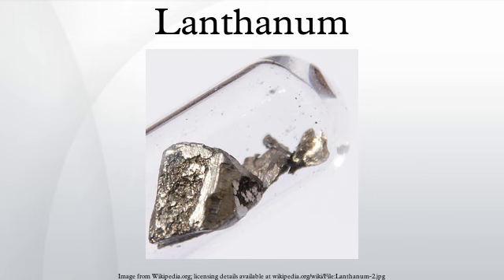The oxides are dissolved in nitric acid, which excludes one of the main components, cerium, whose oxide is insoluble in HNO3. Lanthanum is separated as a double salt with ammonium nitrate by crystallization. This salt is relatively less soluble than other rare earth double salts and therefore stays in the residue. The most efficient separation routine for lanthanum salt from the rare earth salt solution is, however, ion exchange. In this process, rare earth ions are adsorbed onto suitable ion exchange resin by exchange with hydrogen, ammonium or cupric ions present in the resin.